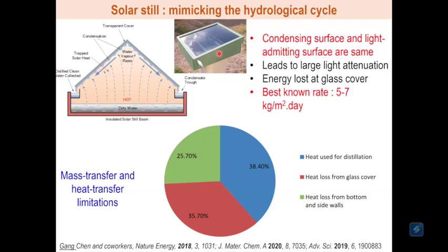These devices won't do any better than nature, which is about 5 to 7 kilograms per meter square per day. That is, you get about 5 to 7 liters of pure water as condensate. And like I told you, the condensation is an exothermic process. It releases heat, which again adds to the efficiency loss. In fact, if you do an energy balance, the heat used for distillation, which is the water vapor evaporation and condensation, is just about 38 or 40% of the total energy that is available from the sun. So this is really the crux of the problem, that a greater energy efficiency is required to bring about better and faster, higher throughputs of clean water from solar stills.